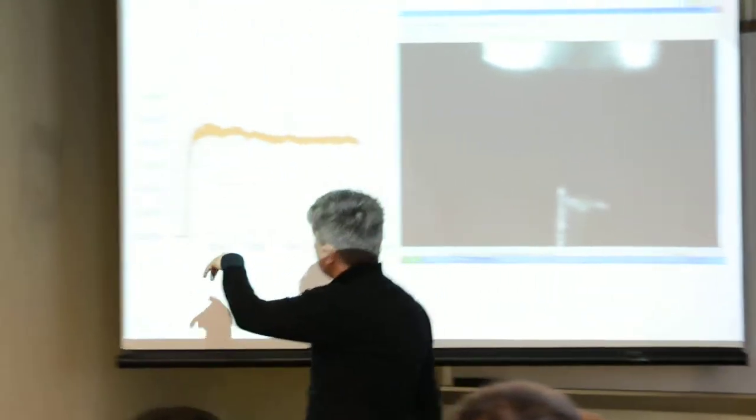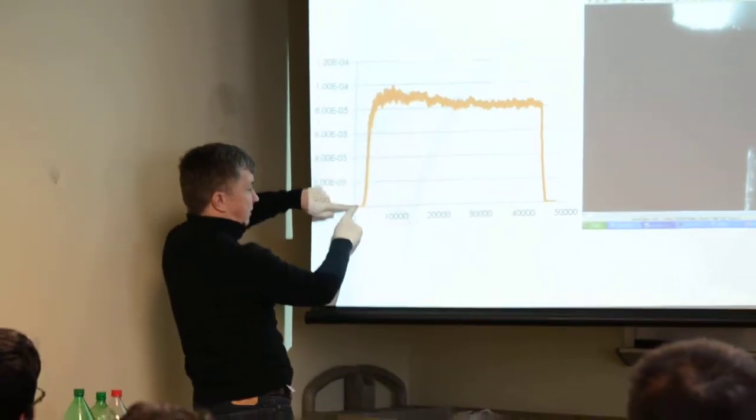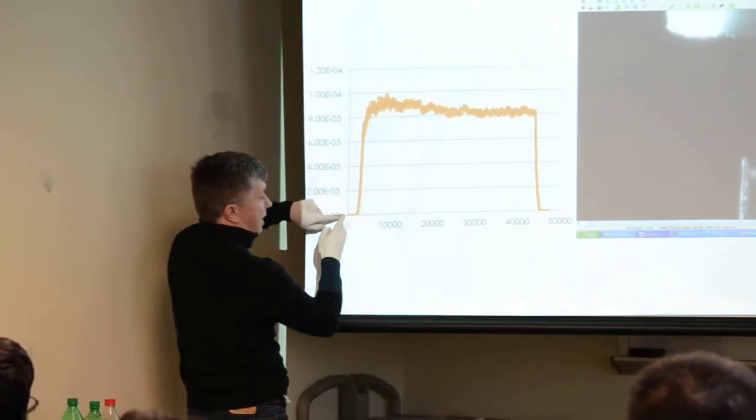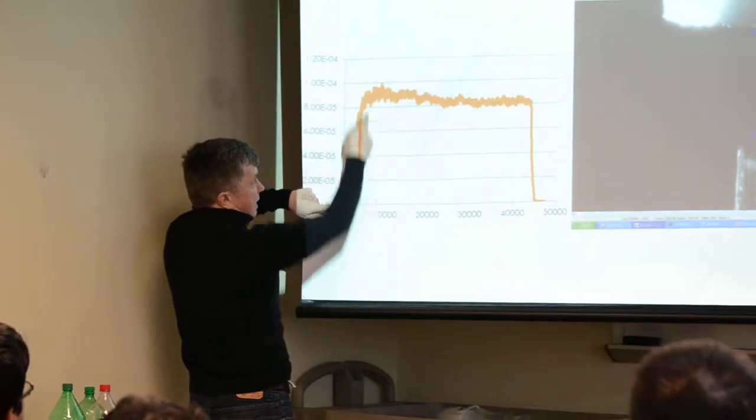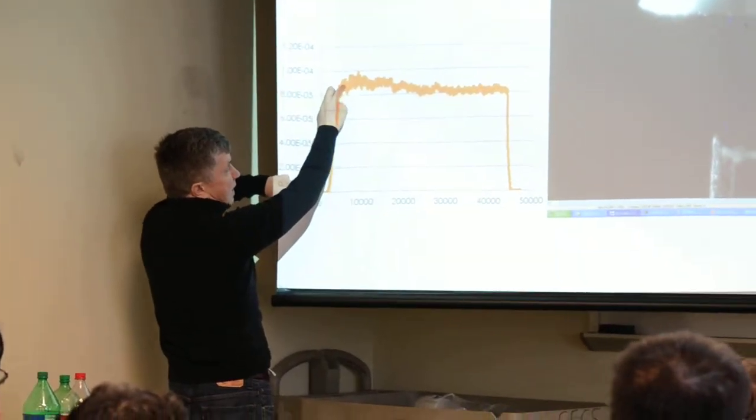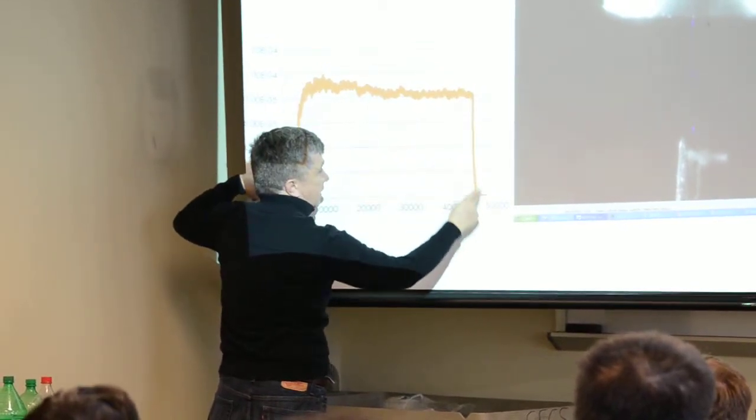The distance is roughly 500 microns. You sweep the voltage from zero to 1000 volts, stay at 1000 volts for about an hour, then bring it back down. As a function of time, what is your current doing? You start at zero volts. At 200V you start to emit. This is a function of time. At this point, you reach maximum 1000 volts, then leave it there and go for lunch.